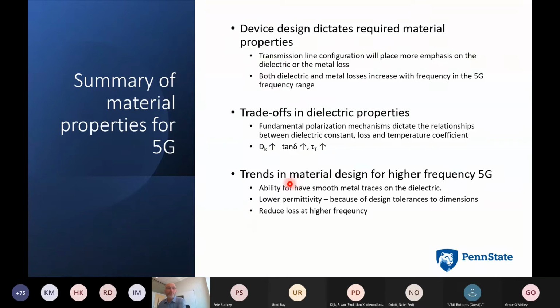And then we know that the trends really, as we push toward these higher frequencies, we know we're going to have smooth metal traces. There's lots of great literature and tutorials here on using smoother substrates to get basically smoother conductors, and then your skin depths are smaller as well, and you're basically then lowering the loss of your transmission line by having a smoother conductor trace. Lower permittivity, definitely. We're not so worried about dimensional tolerances, or I guess we're always worried about dimensional tolerance, but just the actual dimensions. And we need to reduce dielectric loss at high frequency. So I think these are the trends that I see based on some of the devices we're focused on.